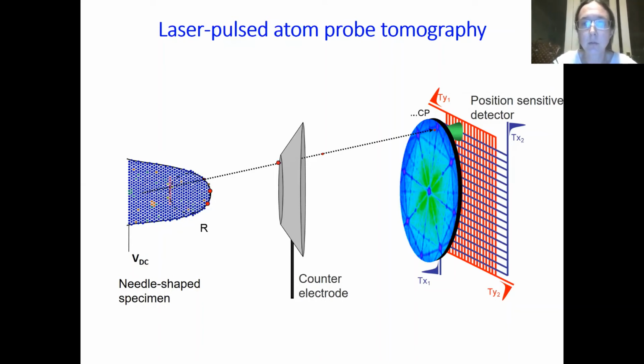The laser pulse will encourage atoms to evaporate, as I'm showing on the screen, one by one from the tip. We need to get just the right amount of laser pulse because we just need to tickle it to kick off one atom. We don't want half the tip exploding, which does happen when the experiment goes wrong. Those atoms, one by one, fly along these trajectories, which are determined by the radius of the tip, and they hit the detector.